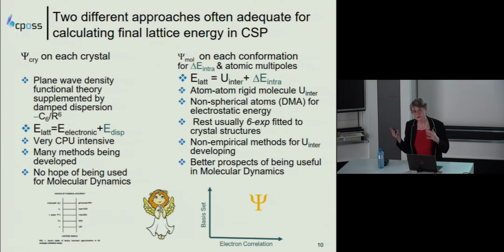The method my group uses, though we may in the end do periodic DFT plus D on selected crystal structures just to see how much the choice of method determines the relative energies, is to do the wave function on the isolated molecule and then analyze this charge density to get a representation of the charge density in terms of charge, dipole, quadrupole, etc. on every atom to represent the lone pairs and pi electrons that determine the directionality of hydrogen bonding, pi-pi stacking, etc. And use that in a model atom intermolecular potential that is anisotropic.